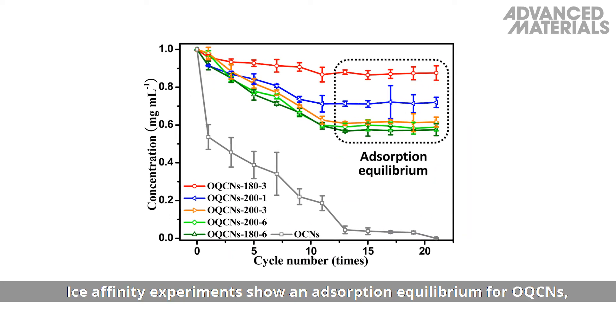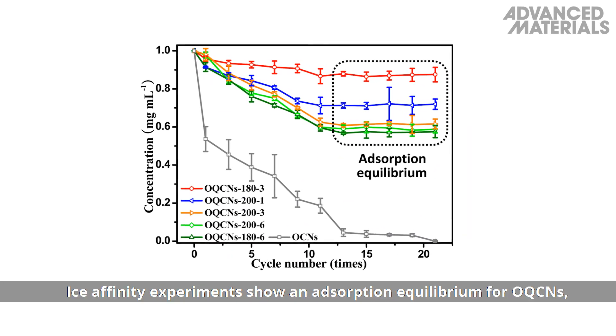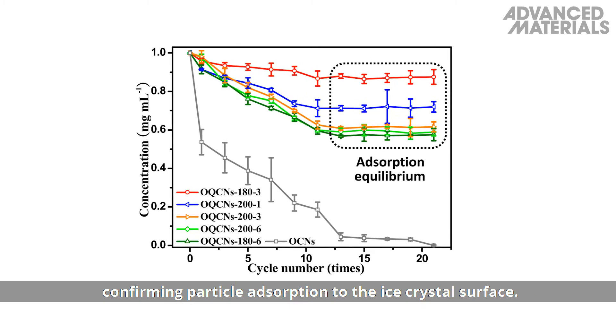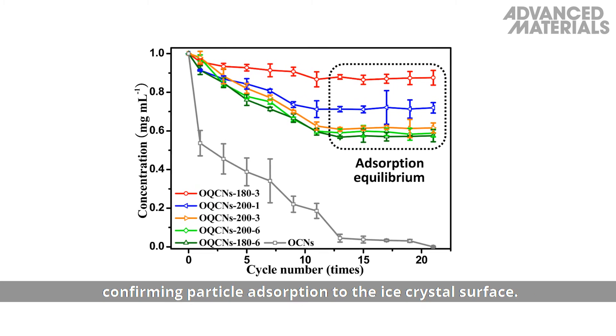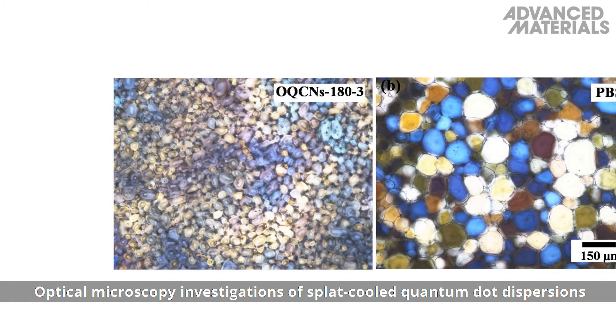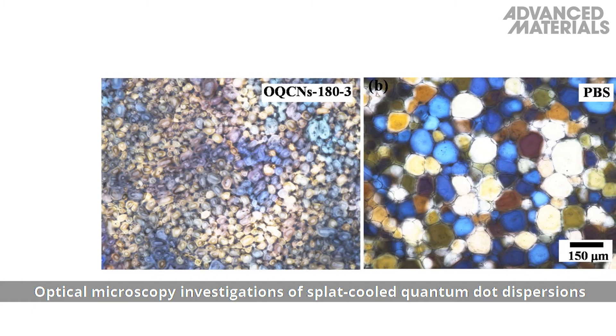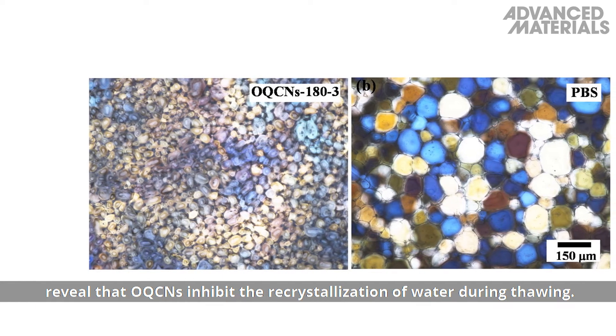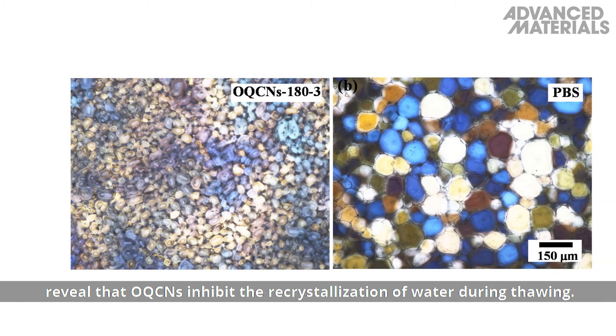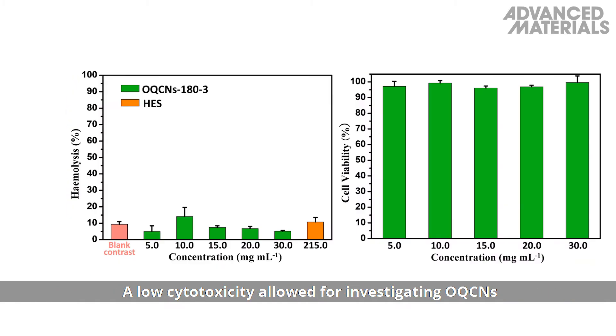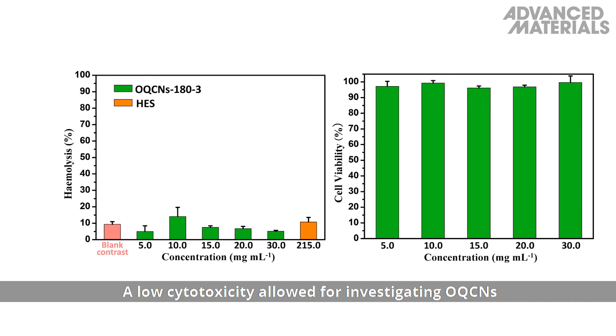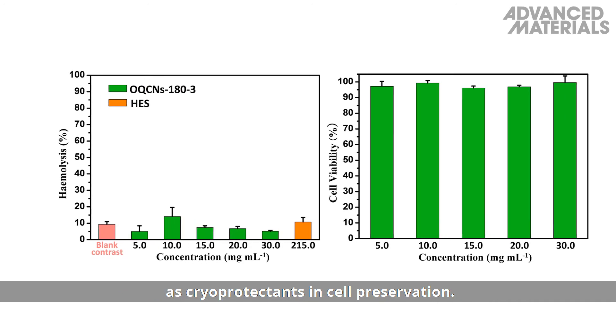Ice affinity experiments show an adsorption equilibrium for OQCNs, confirming particle adsorption to the ice crystal surface. Optical microscopy investigations of splat-cooled quantum dot dispersions reveal that OQCNs inhibit the recrystallization of water during thawing.